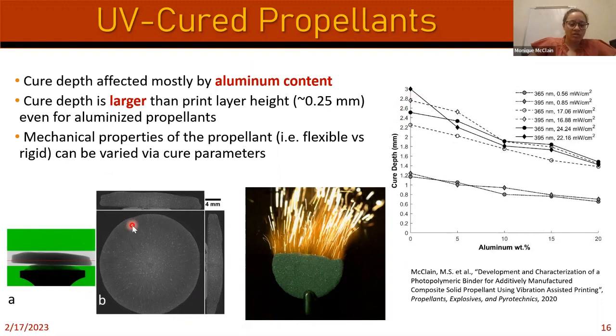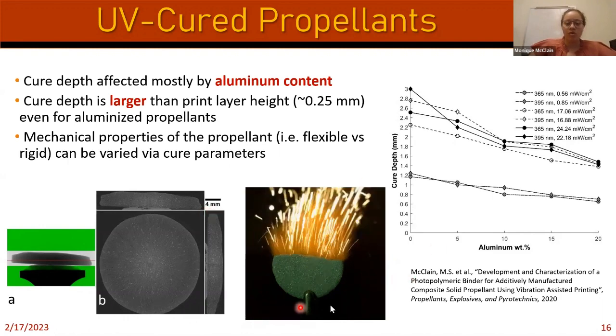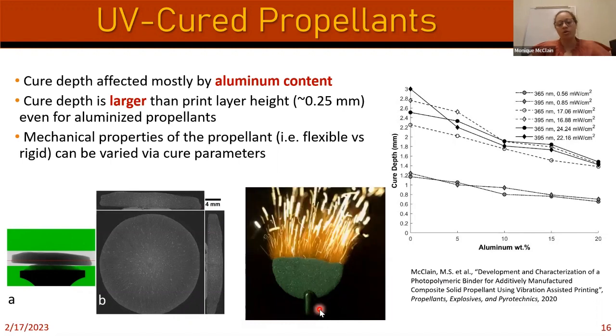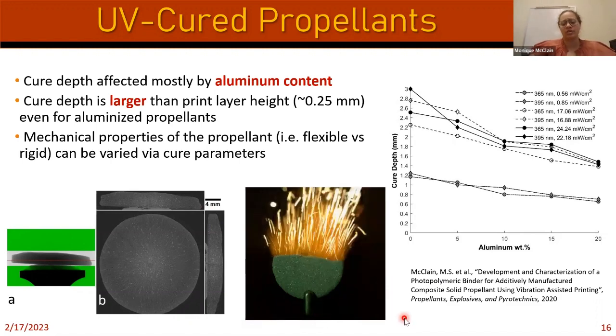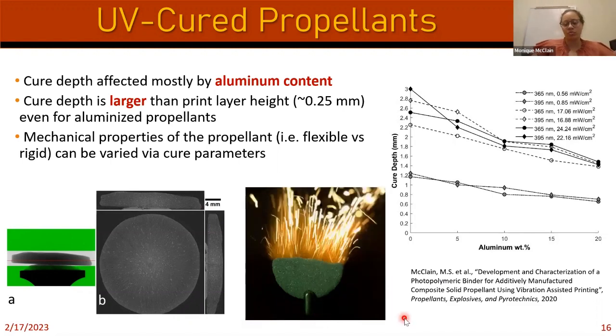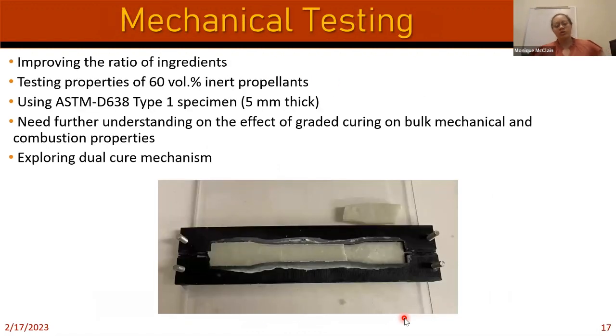Also, just as a side, this is a sample that we micro-CT'd of 4 different cured layers. So there were no obvious issues here, but again, we have to do more mechanical testing. And this is just demonstrating that with the photopolymer, this propellant will still burn. But we still need to characterize the combustion properties of these photopolymers. So this here's a teaser for what we're working on next.